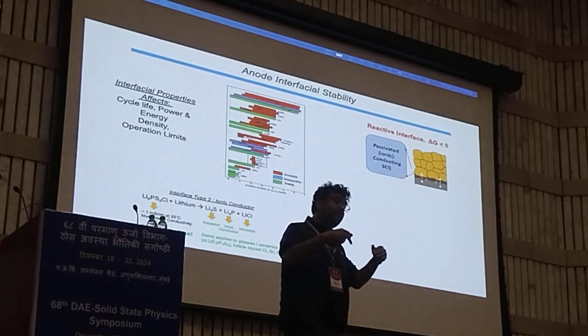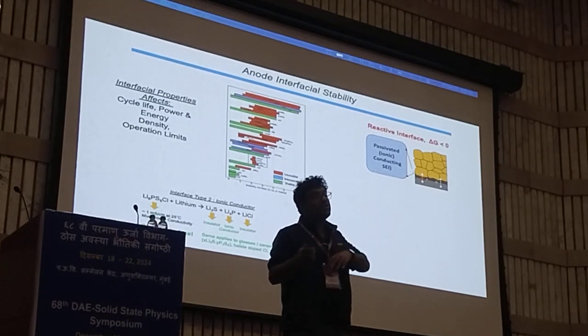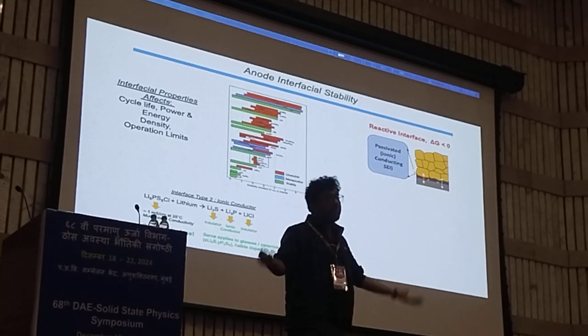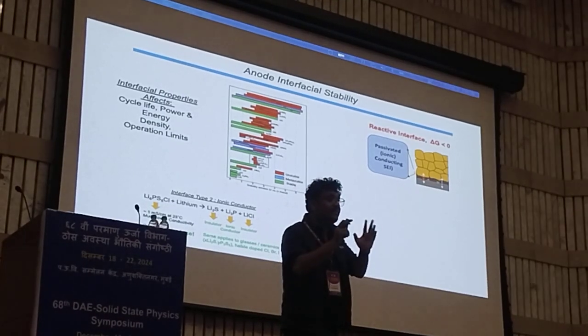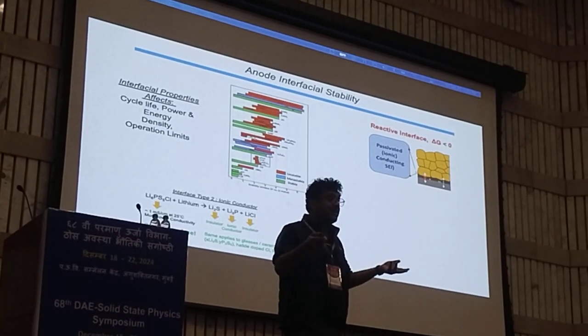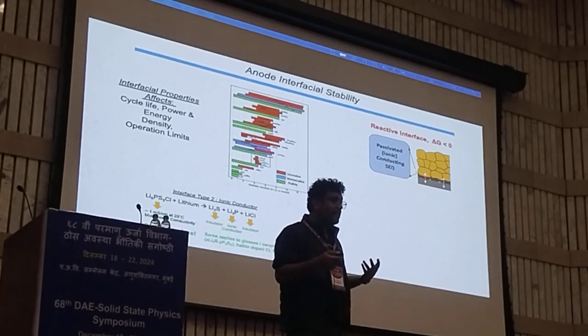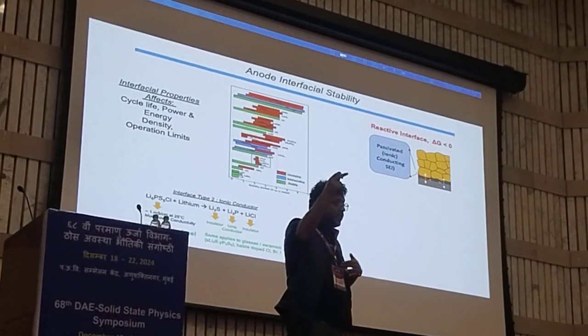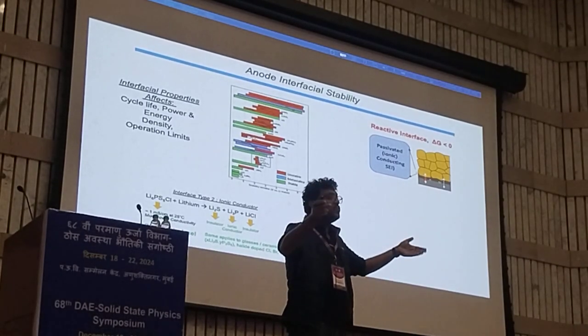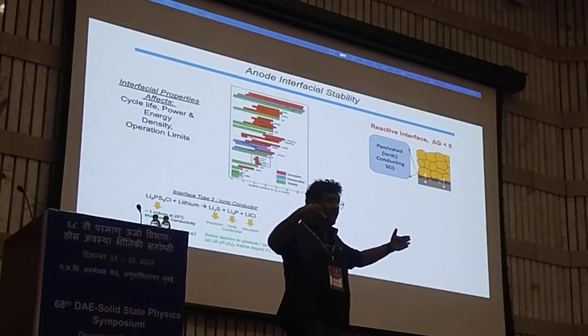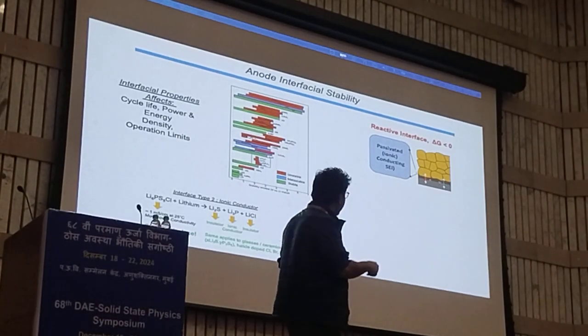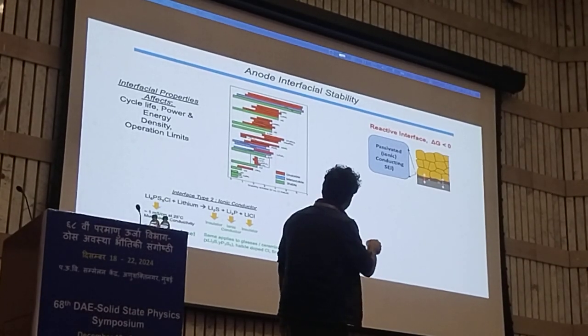But what I mentioned here is not the stability matter. It is the electrochemical thermodynamic stability matter. The most important thing is, once it is decomposed, whether the interface has been passivated or not. For example, the liquid electrolytes we use for batteries nowadays are not thermodynamically stable at the voltage we want. But they decompose to passivate the interface. Once the passivation happens, there is no further decomposition. The same thing happens for this sulfide also.